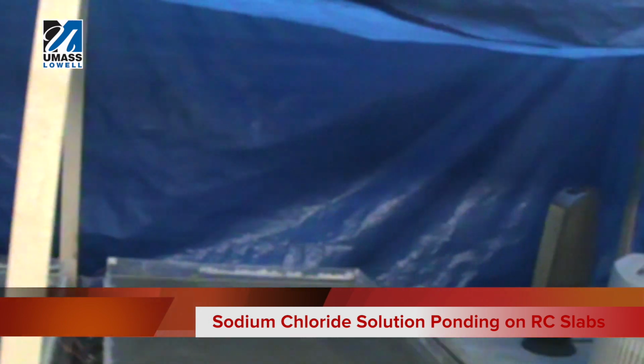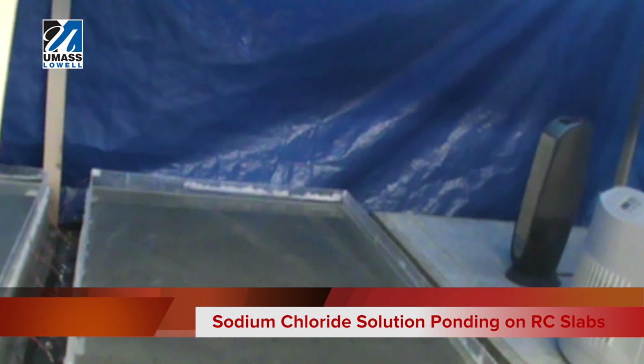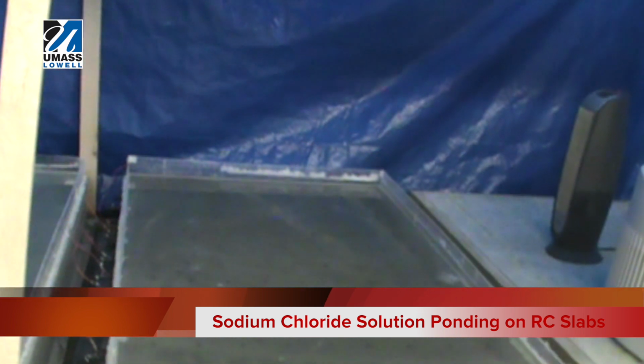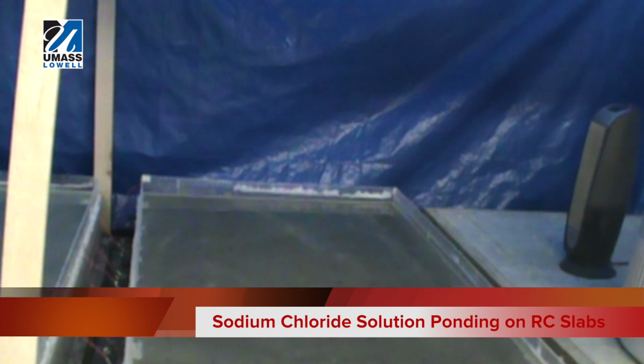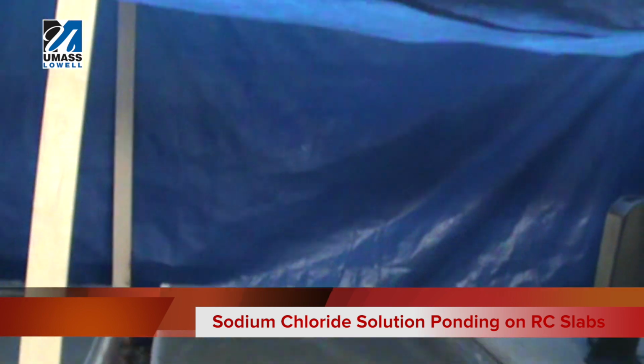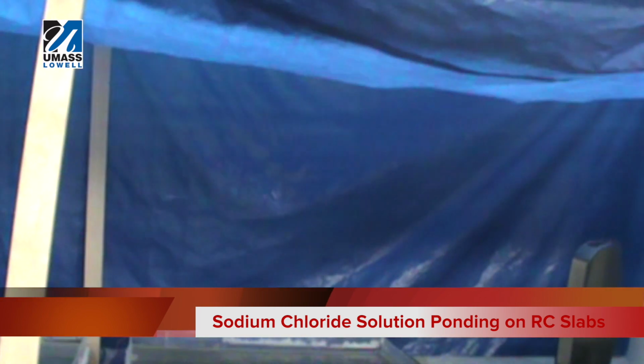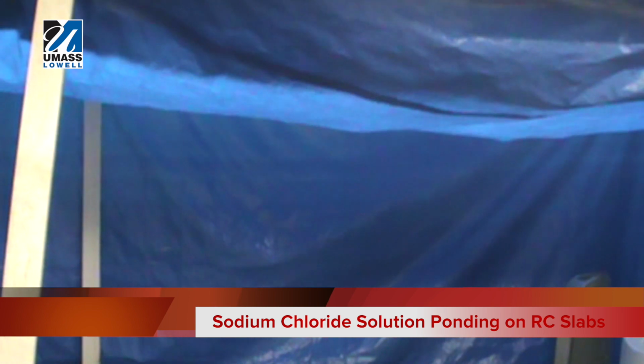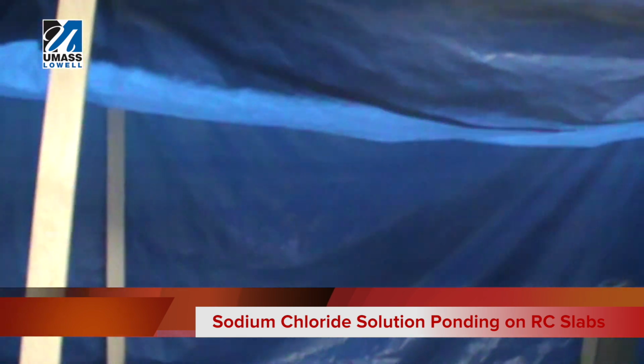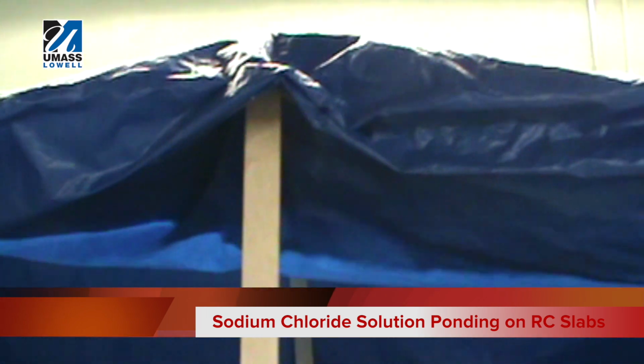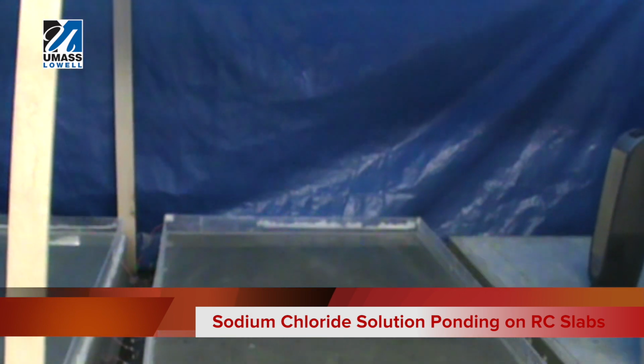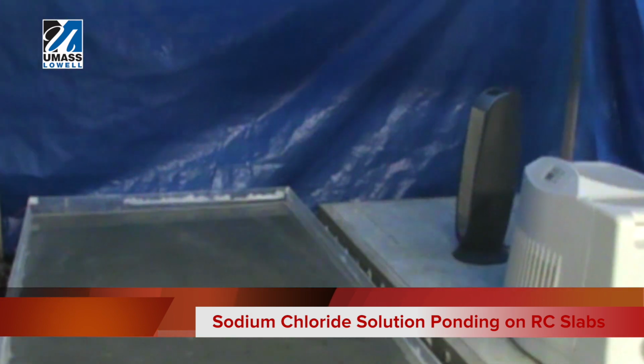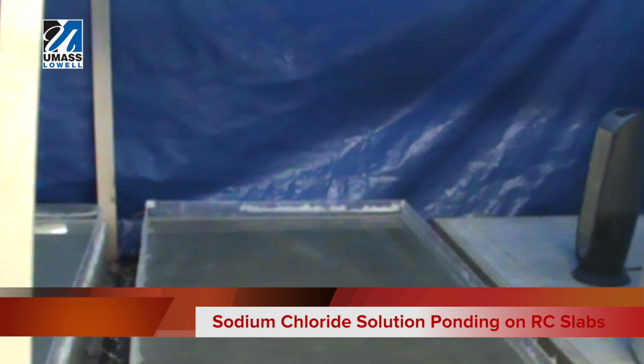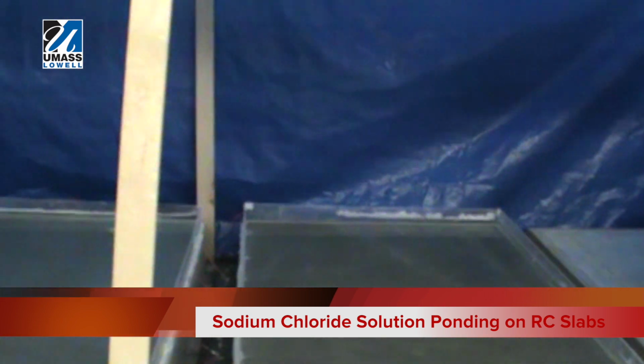During the 4-day wet cycle, the ponds are subjected to 50% relative humidity and a 90-degree Fahrenheit temperature that is controlled by this blue tarp that you see in the top. While in the curing period, in the dry period, the slabs are cured at 72 degrees Fahrenheit and also at a 50% relative humidity ambient.